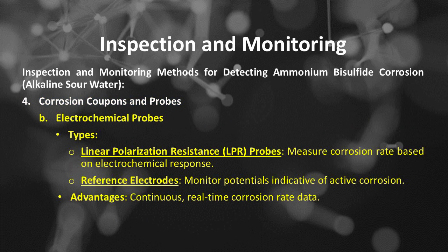Number B is electrochemical probes. The types of electrochemical probes include linear polarization resistance, LPR, probes, which measure corrosion rate based on electrochemical response, and reference electrodes, which monitor potentials indicative of active corrosion. The advantages of electrochemical probes: continuous, real-time corrosion rate data.